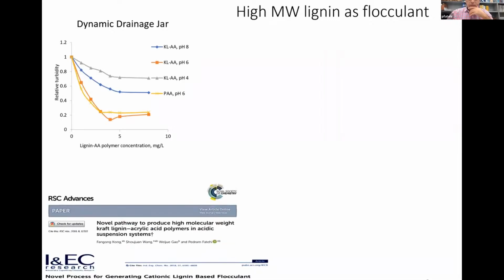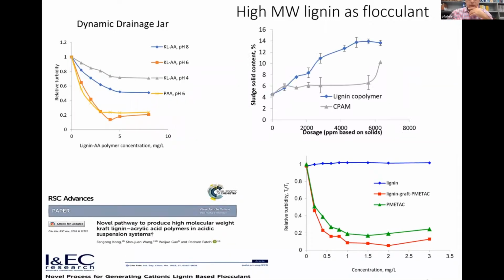So we have tested our material in the wastewater system. So basically here we compared our product with the synthetic one. The synthetic one is the monomer that we produce under the same condition, but without lignin. So you can see that at different pH, of course, we have different efficiency. But when we compare the yellow and orange one, we can see that we got similar or better result for our lignin containing material. Again, this is for anionic one, and this is for cationic one.